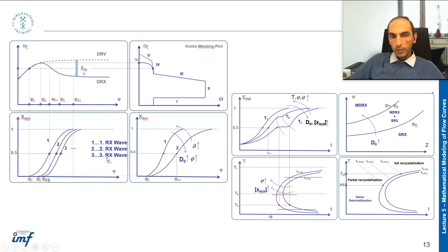second wave, and third wave show that in practice, of course, you do not have a single curve. It's not like the grains start the dynamic recrystallization and then are fully recrystallized at X equal to 1. Instead you have different waves of recrystallization.